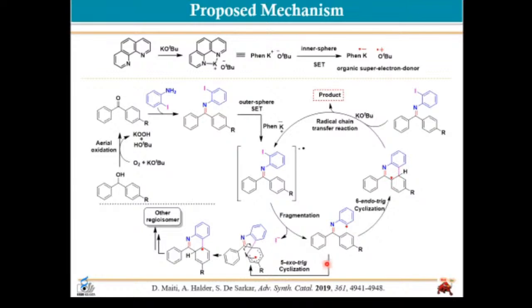And as you remember, I told you about formation of an isomer. So how is that possible? Because after this radical, in the normal case, it forms a new carbon-carbon bond here, a six-membered ring directly. Now a five-membered ring is also possible here, because it's a double bond, right? The radical can add here and add here also. If it adds here, then it goes via this five-membered intermediate, and there is a little bit of rearrangement here, carbon breakage, and you form the other isomer. You see, in this case, R is here in the para position. Now, because of this rearrangement, our group shifted one step here, and you form ultimately the product, with a double bond formation here. That is the targeted heterocycle. But because of the rearrangement, this R shifted one position. Just by proposing this mechanism, we also explain the formation of different isomers.